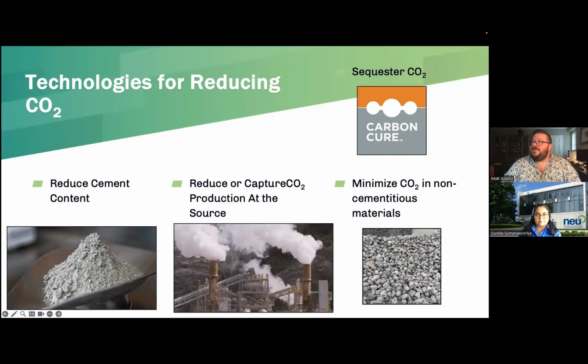There are a number of technologies for reducing the CO2 related to concrete. First options are sequestering the CO2 into concrete. So these are technologies like what is being sold by Carbon Cure and Solidia, where you're actually putting CO2 into the concrete and locking it away. I'm not going to touch too much on that today. You can reduce your total Portland cement content and your total cementitious materials content. We can try to reduce or capture CO2 production at the source. And then we can also try to minimize the carbon in our non-cementitious materials, so minimizing carbon associated with the aggregates and other processes in the concrete production process.